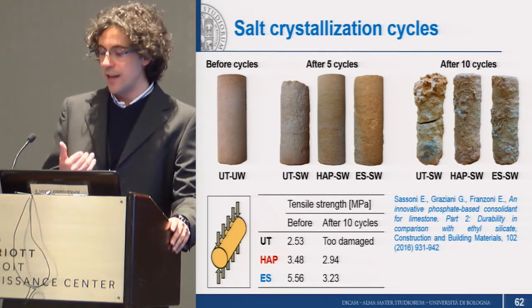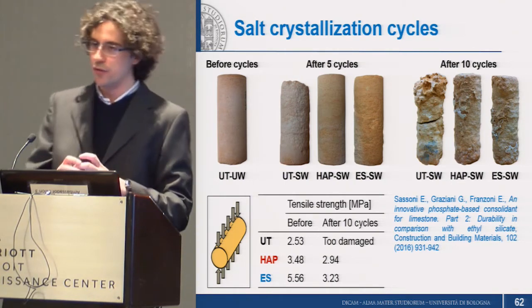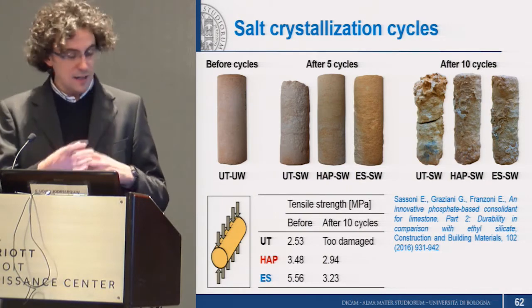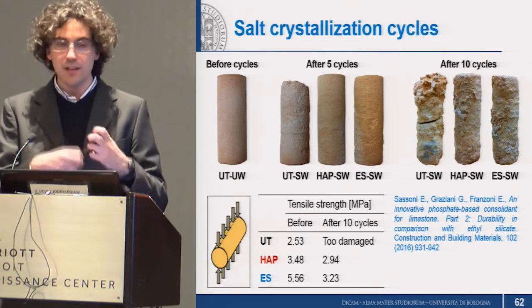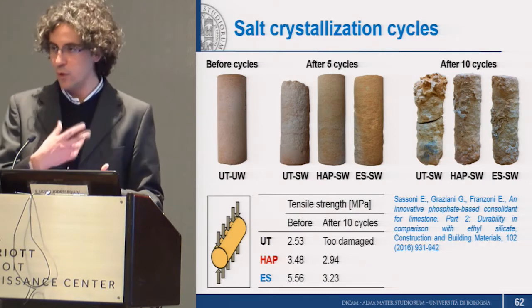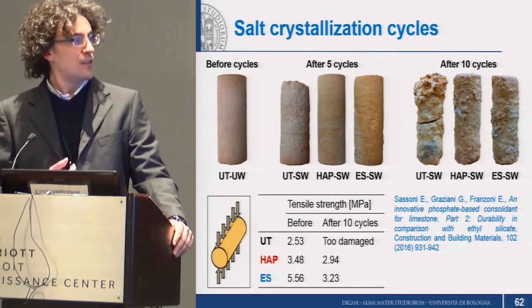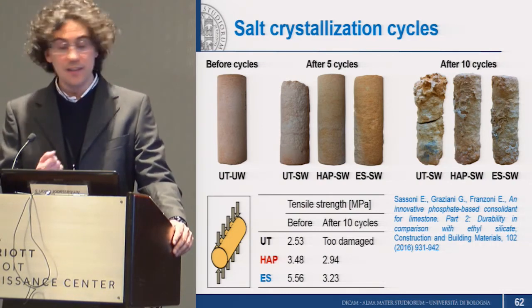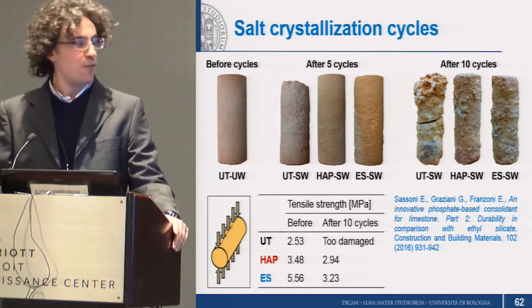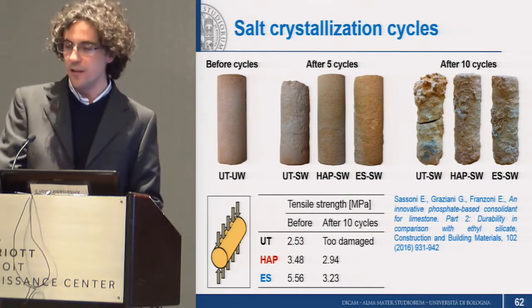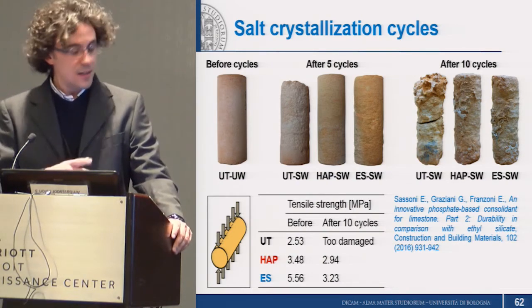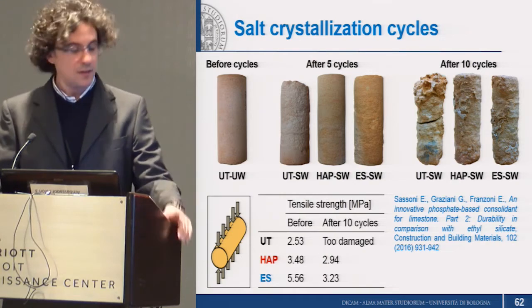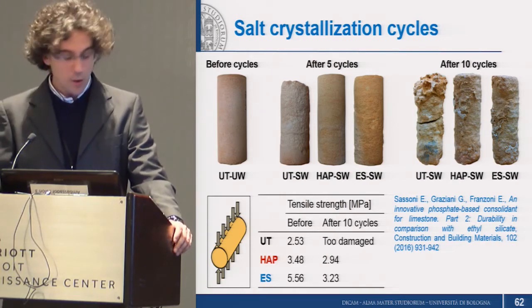In our case, the alterations in pore size distribution were such that there was no dramatic increase in micropores, which could worsen the resistance to ice and salt crystallization, because as I think everybody knows, the smaller the pore, the higher the crystallization pressure. Still, our treatment was able to resist these cycles in a very good and promising way.